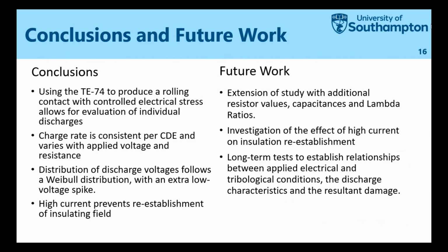And with the high current scenario, it prevents, to a degree, the re-establishment of the insulating field of the oil. So in the future, I'm going to be extending the study with even more resistor values, focusing on the combination of capacitance and lambda ratio, and then a little simple modeling of the contact in ANSYS to verify some of our capacitance assumptions, because classically we assume that the contact area is the capacitor area, but that's being challenged here.